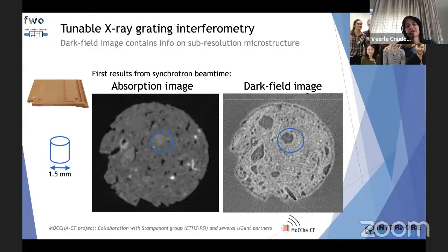So we are now working on a method to be able to say, yes, this zone contains pores between 200 and 600 nanometers, this zone contains pores between 700 nanometers and 1 micron, and this zone contains no pores, something like that. That's something we are working on closely in collaboration with Marco Stampanoni of ETH Zurich and the Paul Scherrer Institute in Switzerland.